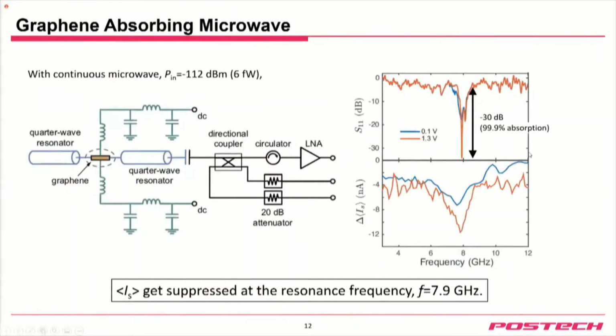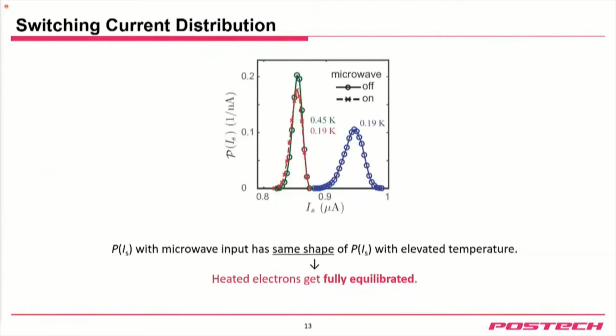So basically, this is the reflectometry, and when we sweep the frequency of the microwave, the reflection decreases down to minus 30 dB at the resonance frequency of about 7.9 gigahertz that we intended. From that, we can infer that about 99.9% of the microwave was absorbed by the graphene. At the same time, the switching current of the Josephson junction shows a clear dip. That means the microwave is absorbed in the graphene, which caused the decrease of the switching current of the Josephson junction. So this is the proof that our Josephson junction bolometer is working.